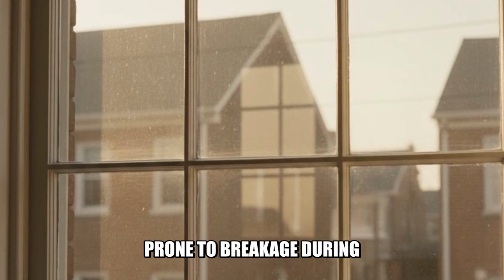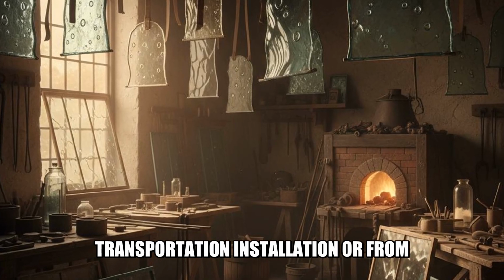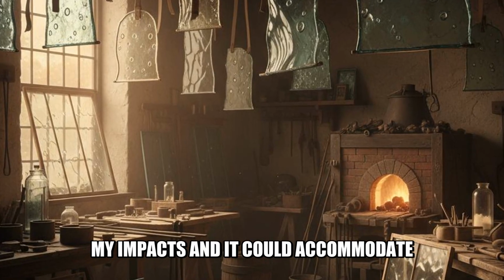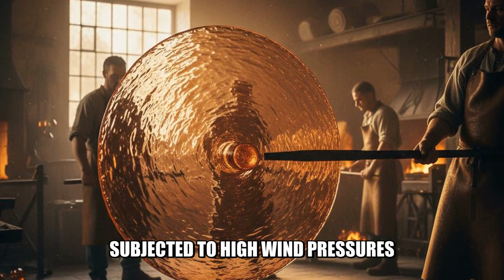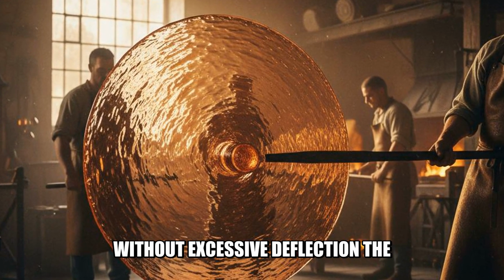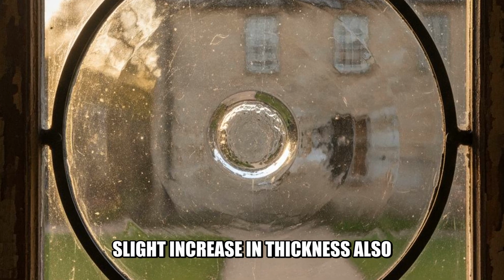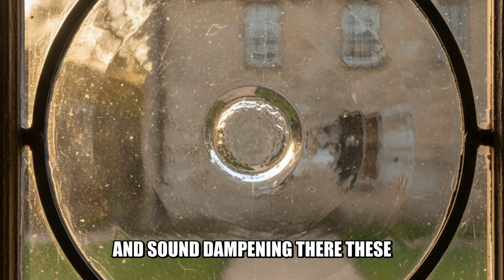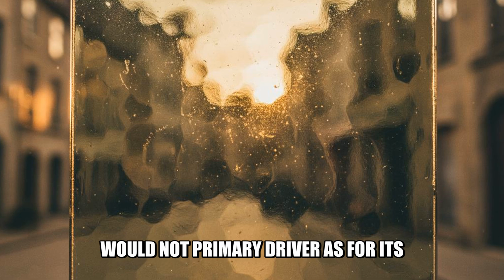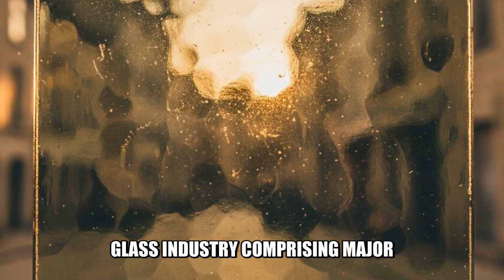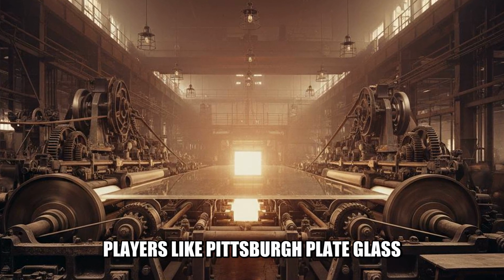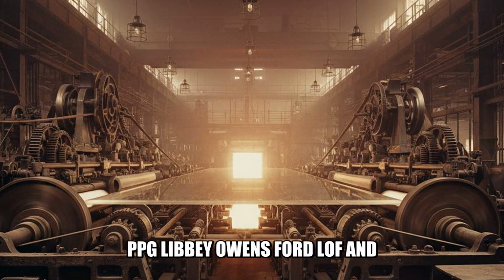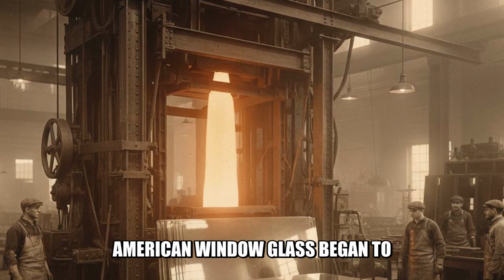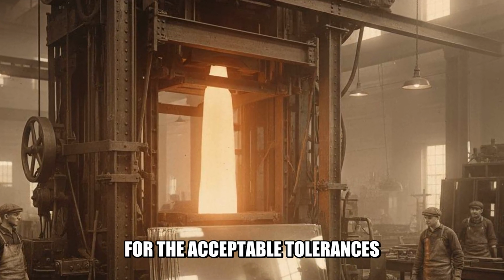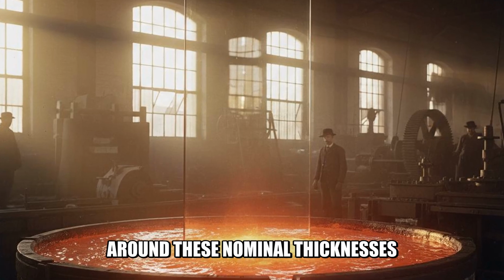It was less prone to breakage during transportation, installation, or from minor impacts, and it could accommodate larger window openings or areas subjected to higher wind pressures without excessive deflection. The slight increase in thickness also offered marginally better insulation and sound dampening, though these were not primary drivers for its initial adoption. As these categories solidified, the glass industry, comprising major players like Pittsburgh Plate Glass (PPG), Libbey-Owens-Ford (LOF), and American Window Glass, began to establish internal specifications for the acceptable tolerances around these nominal thicknesses.